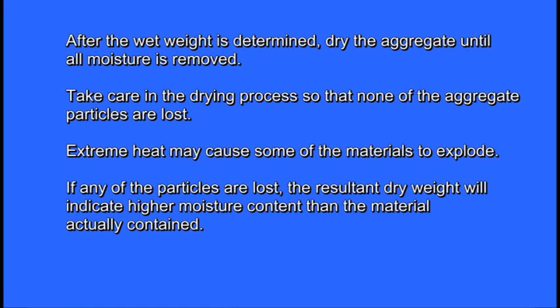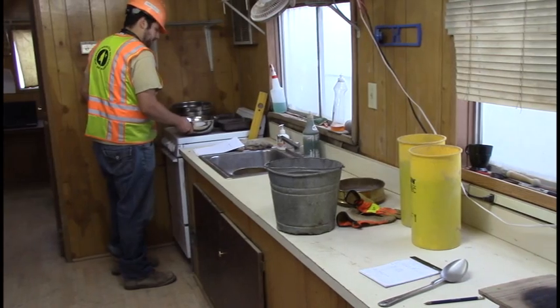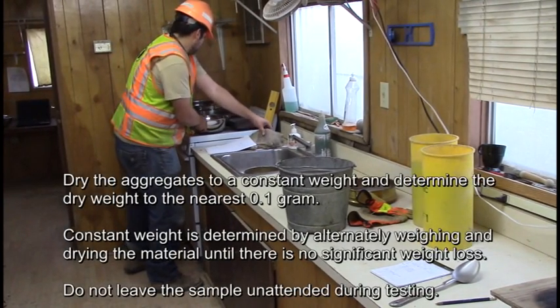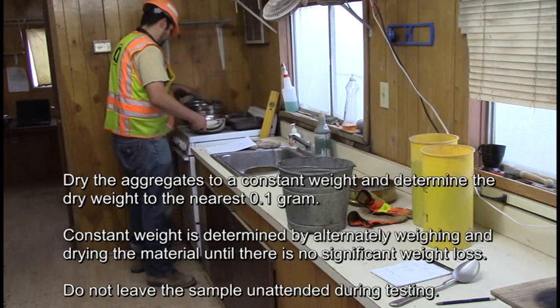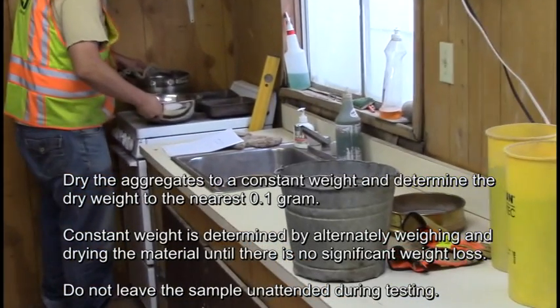After the wet weight is determined, dry the aggregate until all moisture is removed. Take care in the drying process so that none of the aggregate particles are lost. Extreme heat may cause some of the materials to explode. If any of the particles are lost, the resultant dry weight will indicate higher moisture content than the material actually contained. Dry the aggregates to a constant weight and determine the dry weight to the nearest 0.1 gram.